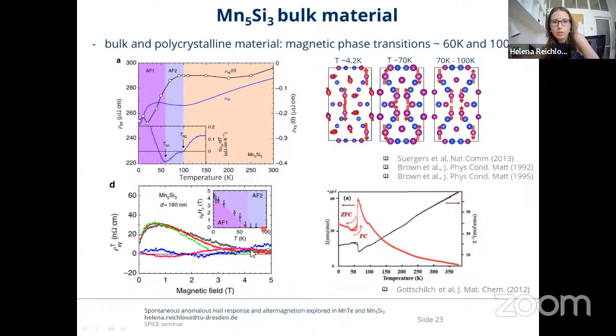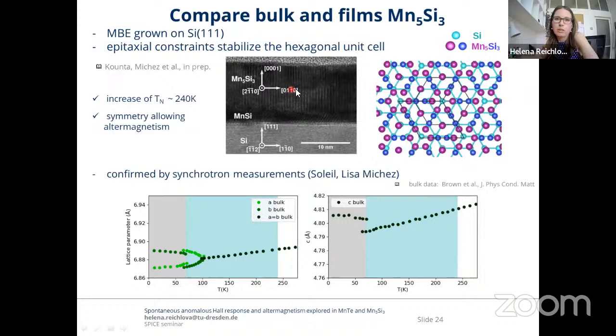Similar transitions were confirmed by the bulk measurements to be approximately between 50 and 100, or 70 and 100 K. And now we prepared the Mn5Si3 by MBE, and we grew the materials on a silicon 111 substrate, which has the hexagonal pattern, and it stabilizes the Mn5Si3 layers into this hexagonal shape. This is actually very important, and I will discuss it now in more detail, because as you will see, this